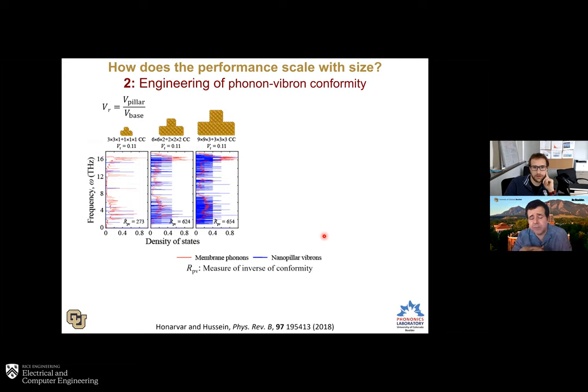So the first thing we've done is we took that unit cell and enlarged it proportionally. So we enlarged the pillar and the membrane proportionally, and we defined a quantity, a metric, VR, which is basically the volume of the pillar compared to the volume of the base. And so when you enlarge everything proportionally, effectively you're keeping VR constant. And we basically quantified that conformity using some algorithm. And this R quantity here quantifies the reciprocal of that conformity. So the larger the number, the less conforming the two density of states are.